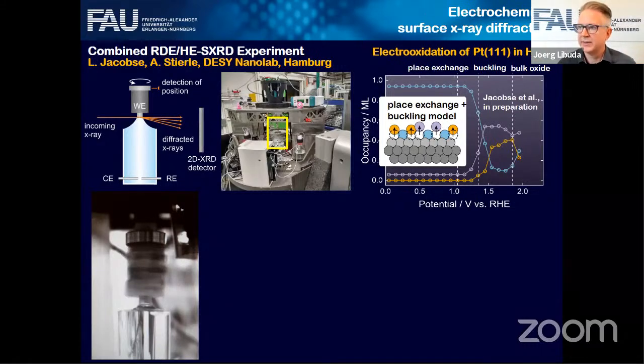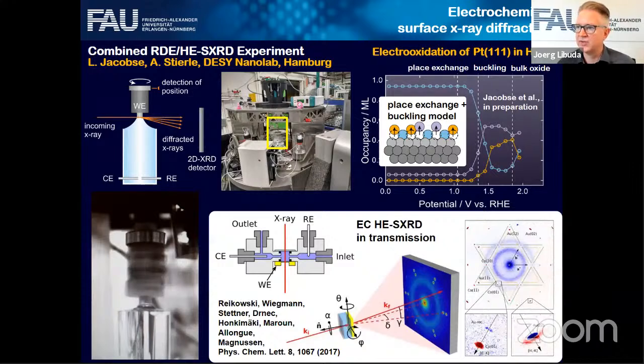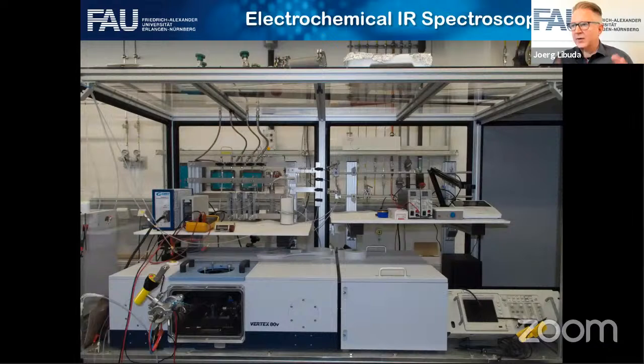There's also another fascinating experiment I would like to draw your attention to, at least from the surface science side. In the meantime, it's also possible to do X-ray diffraction at the interface with high energy X-rays in transmission. So here, this electrochemical cell and a single crystal, and then the high energy X-rays go right through this interface. In such an experiment, it's actually possible to see the very interface. For surface scientists, this experiment is really fascinating because the diffraction pattern very much looks like a low energy electron diffraction pattern. So any surface scientist will be quite excited.